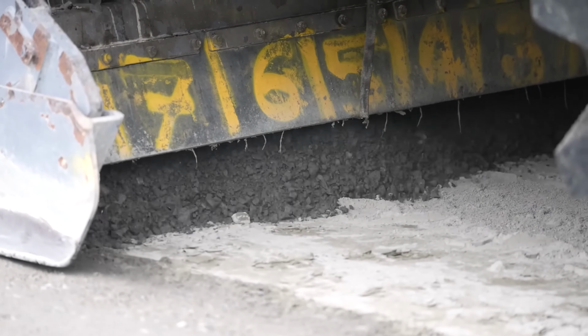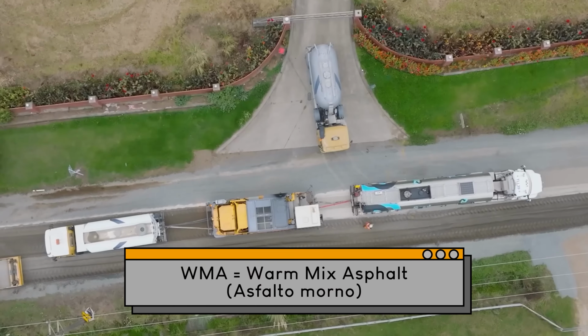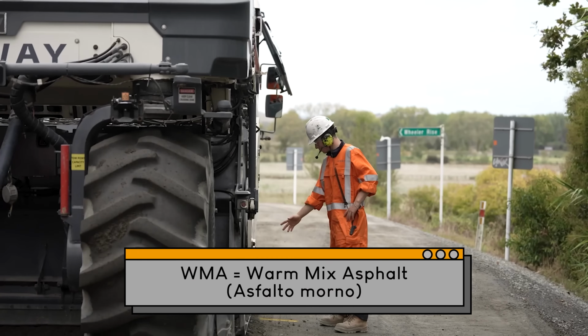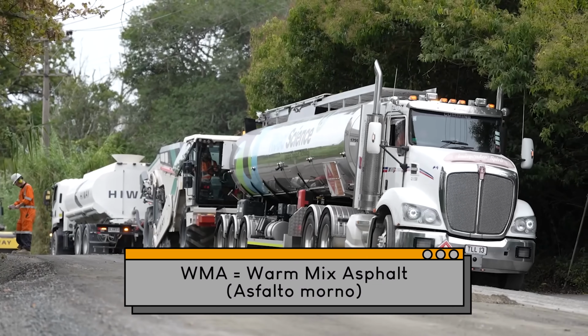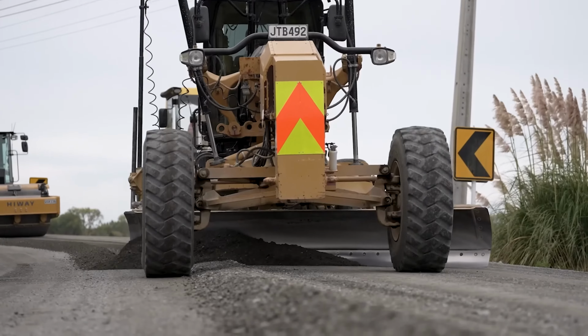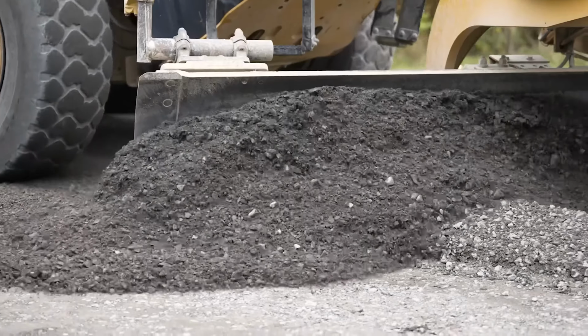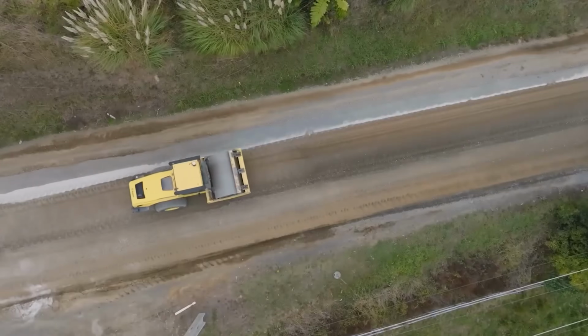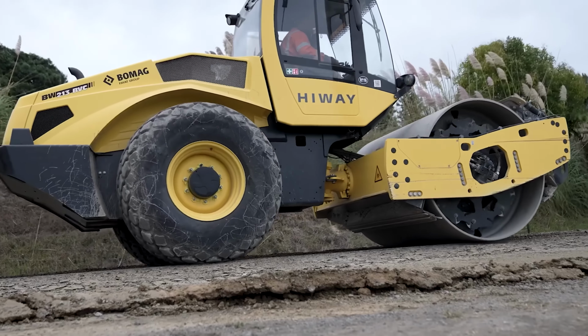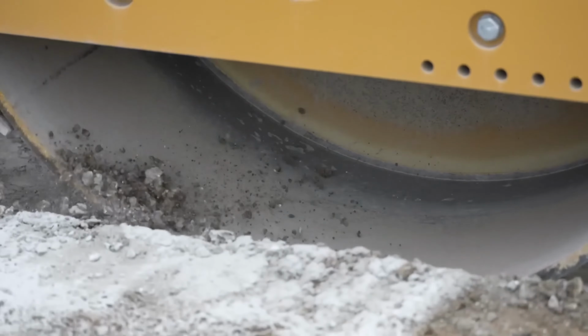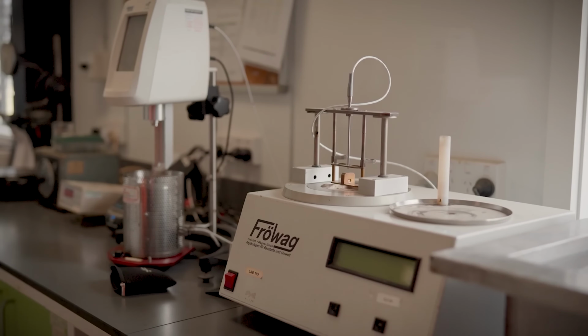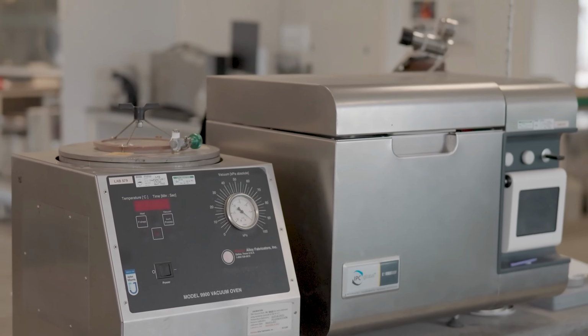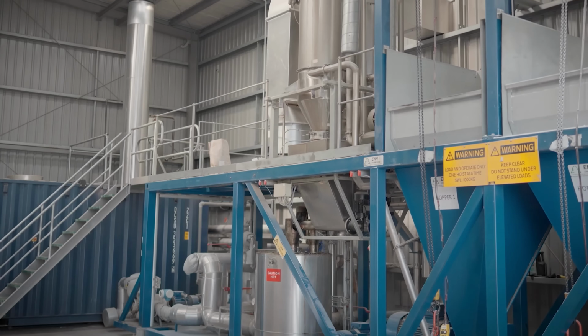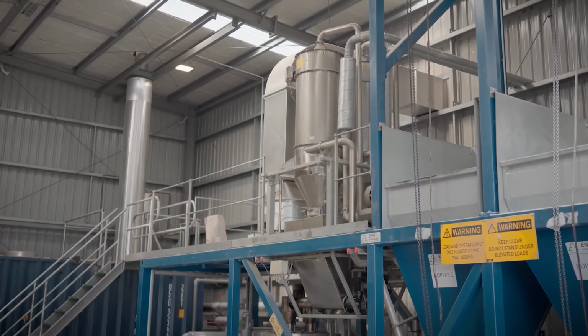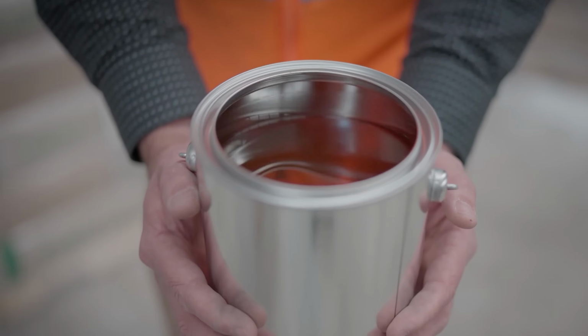Innovations like warm mix asphalt, which can be produced at temperatures between 20 to 40 degrees lower than conventional ones, reduce carbon dioxide emissions, and additives like used tire rubber or polymers increase its lifespan. However, challenges remain. The dependence on petroleum makes asphalt sensitive to price fluctuations, and research is seeking sustainable alternatives, such as bitumen derived from biomass or microalgae.